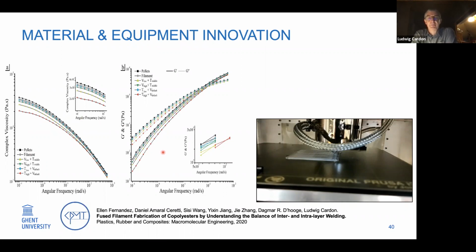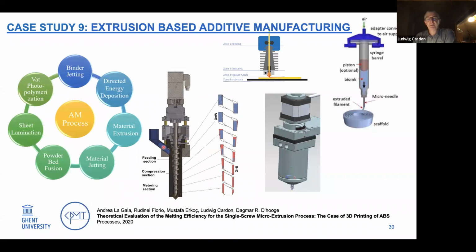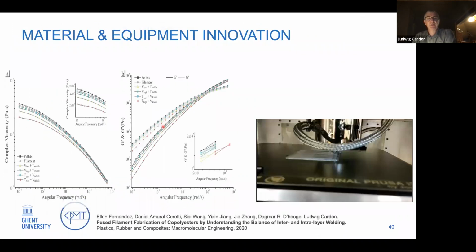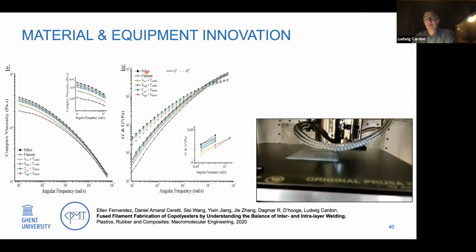One thing we also combine in this stage is that we also try to find out the aging. What do I mean by that? So when you process a pellet or a filament, when you use a pellet immediately, as mentioned before in this slide, we have one-time heat transfer in the polymer. But when we need to use a filament, we first have to produce the filament, and then we use the heat in the nozzle to deposit the material. So what we investigate here is the flow behavior of a pellet, what's the second heating of the material in the filament, and then afterwards, after deposition.